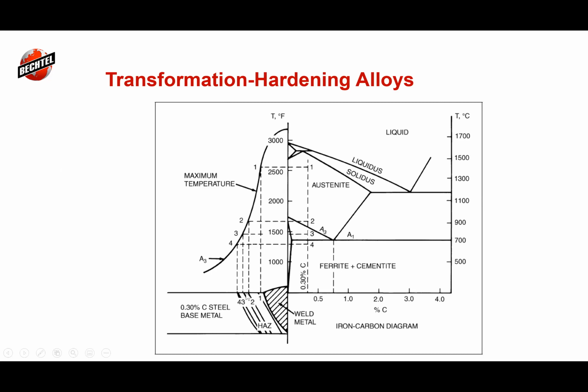Like that picture I showed before, if we're right there at the fusion line, it comes up almost to where it's liquid in this region. And as we move maybe a millimeter or 2 millimeters away, the maximum temperature is still austenite, but it's not nearly as high. Each one of these is seeing these different waves as they're coming off, and we have this whole difference in microstructures that's occurring.